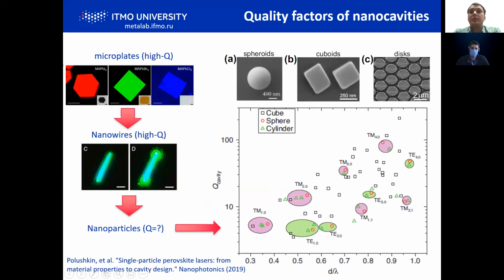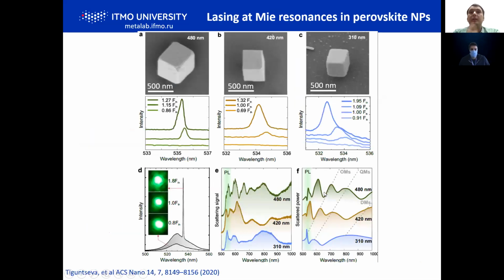Interestingly, for sizes less than one wavelength, in principle, cubic shapes give comparable or sometimes even better quality factors as compared with spheroids. So it means that we don't need to use spheroids with a lot of defects, because obviously these cannot be single-crystal spheroids. They are of course polycrystalline with an amorphous shell material with a lot of defects, but cuboids are much better in this regard. And in our recent work, we tested various perovskite nanocuboids and observed the threshold-like appearance of a lasing line.